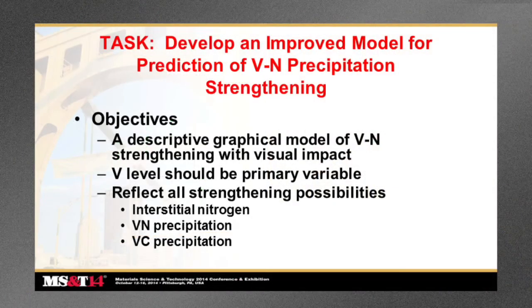The objective for improving the model then was to develop a descriptive graphical model of vanadium nitrogen strengthening that would have visual impact for sure, and also that vanadium should be the primary variable, so you can then quantify the relative effects of vanadium and better design your alloy content.